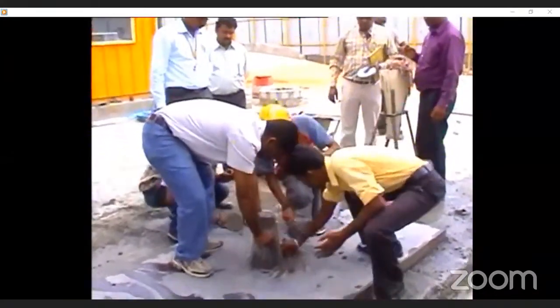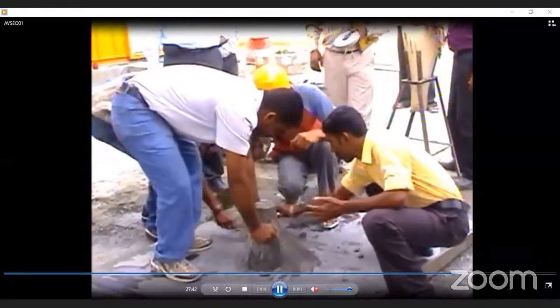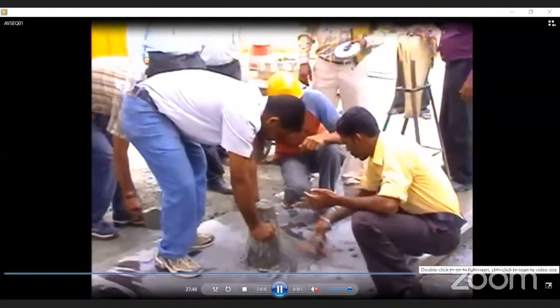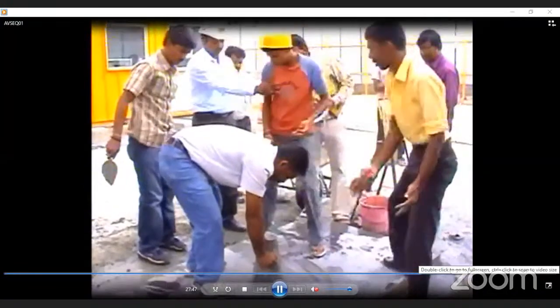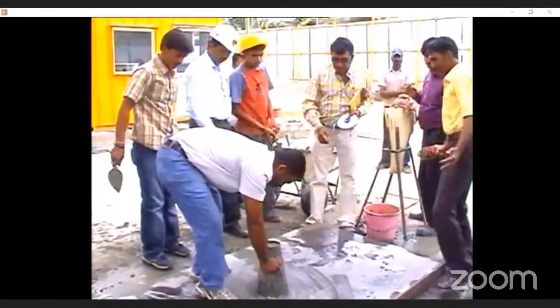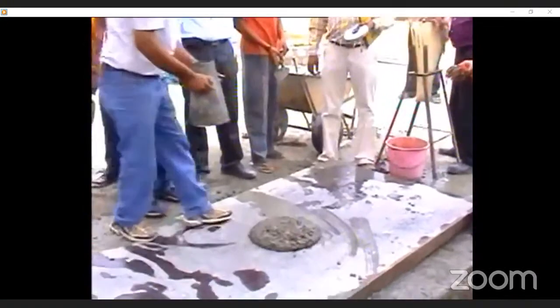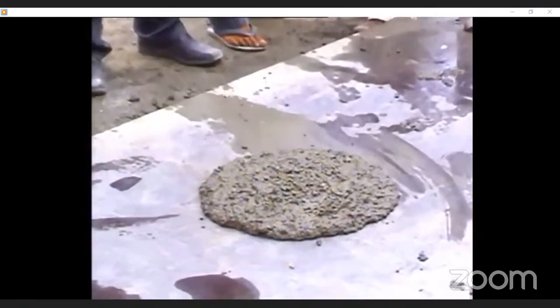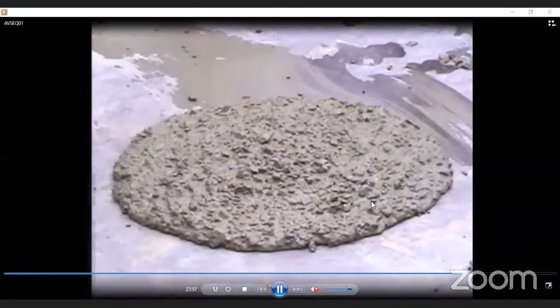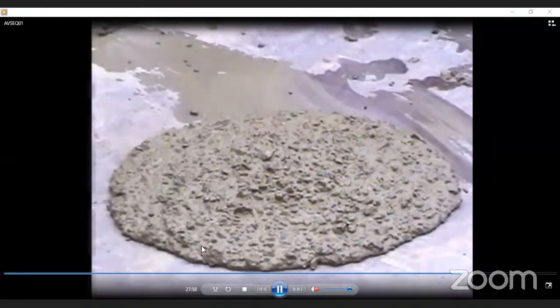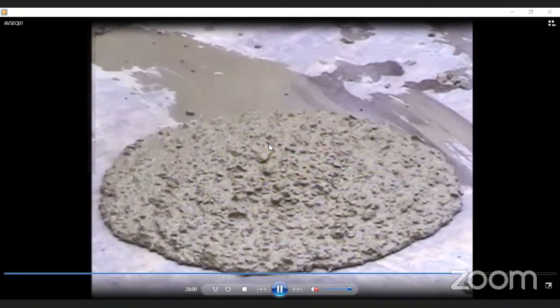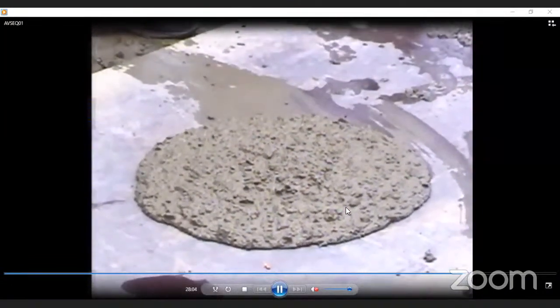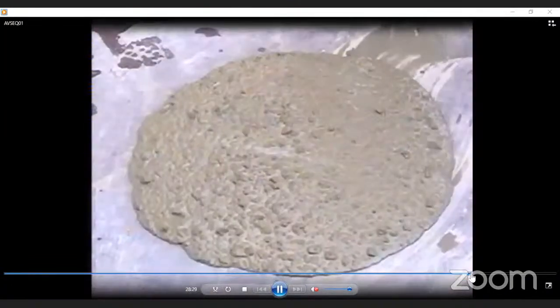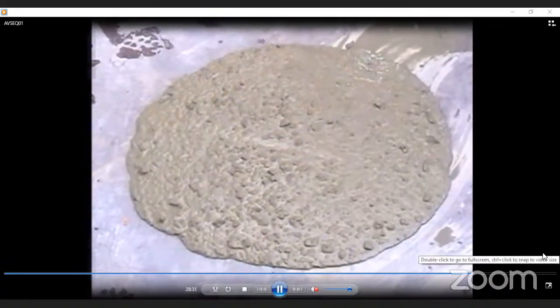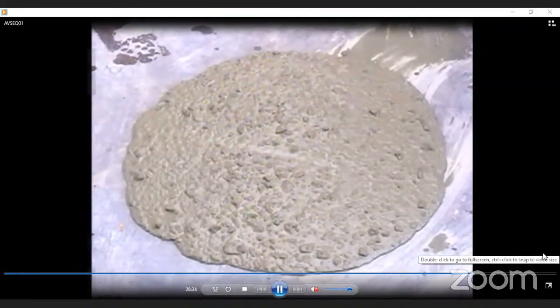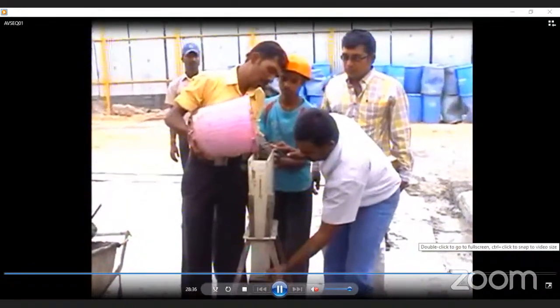This is in the plant also, we have checked and we supplied altogether 355 cubic meters over a period of 2.5 days, continuous. This is very, very important: the flow of the coarse aggregate to the periphery of the circle. It should not stagnate only at the middle. Also, we have checked the V funnel. This is the top view. This is the V funnel test.